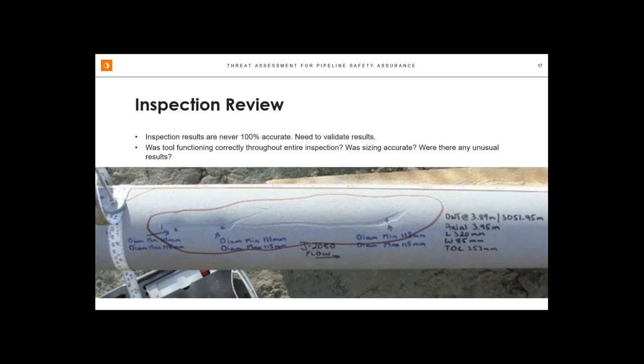So our QAQC process on the ILI that was run on this pipeline identified this as a dent with metal loss that had a very, very unusual profile. And it didn't look just like a dent that was coincident with corrosion, which was what it was reported as. And so we wound up flagging it, recommending it for inspection, and then it turned out to be a gouge, and that was a code mandated repair. So this particular joint of pipe eventually got cut out and replaced.